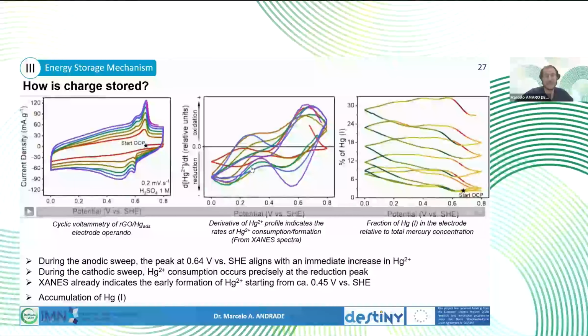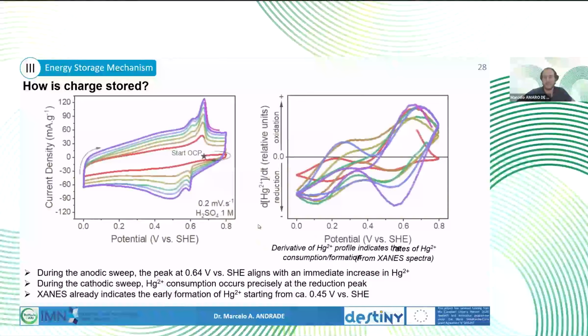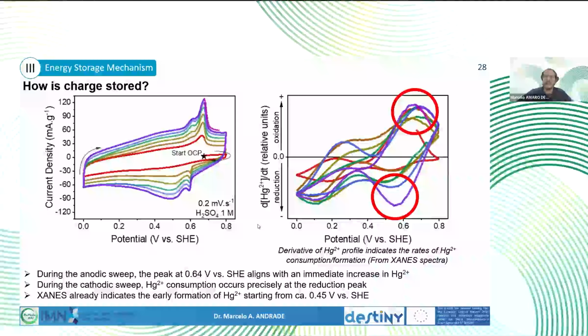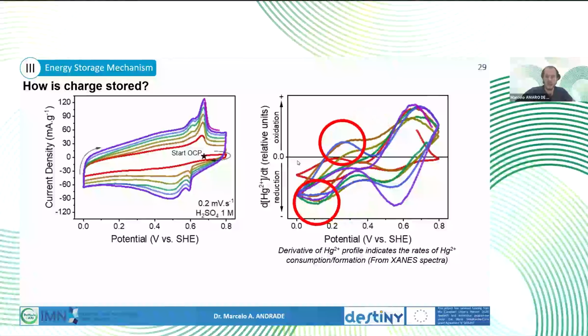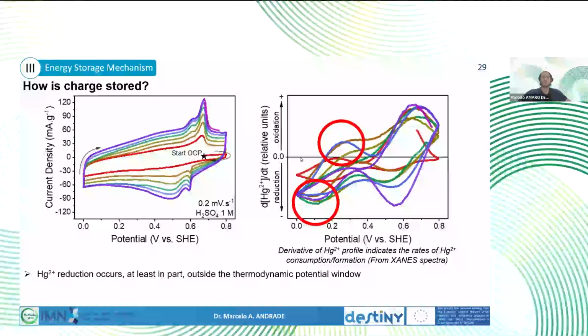Another interesting feature here is this part between 0 and 0.2 volts versus SHE, where mercury 1+ is irreversibly produced and mercury 2+ is mostly irreversibly consumed. And that can be seen more clearly on this slide. First, you have the oxidation peaks, which we see in electrochemistry. And then we have these areas that do not correspond to any electrochemical signal.